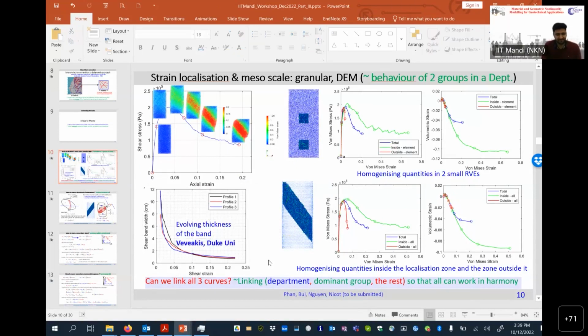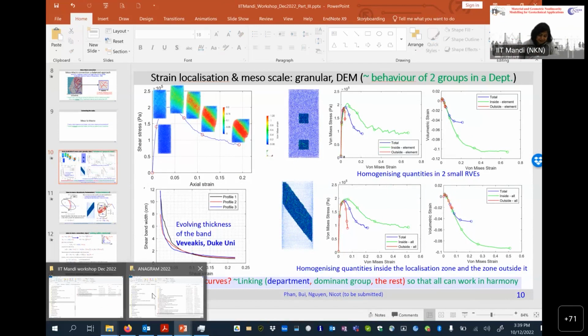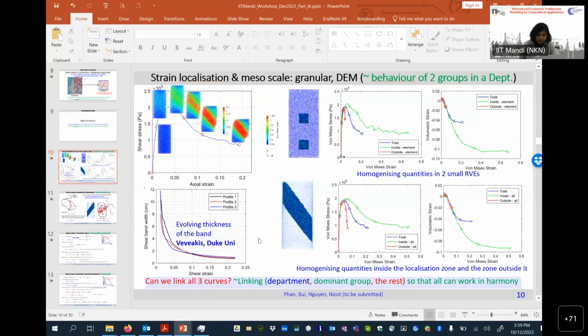Yeah, thank you, Giang. In that regard, I have a continuing question. When we showed this plot for the thickness calculation, it was strain. Now, when we have DEM simulation, we have multiple parameters. We can have an assessment over relative displacement, rotation, strain also. What we noticed while doing the fit is that all of these parameters may not give the exact same length of the shear band. The relative displacement is more of an independent parameter rather than strain. So any observations on that? Which parameter might be a better quotient?